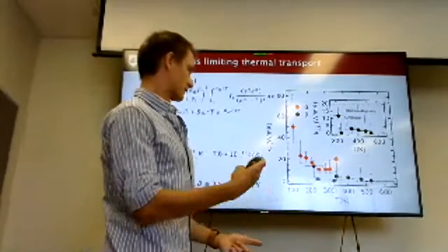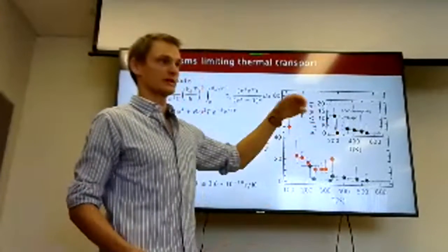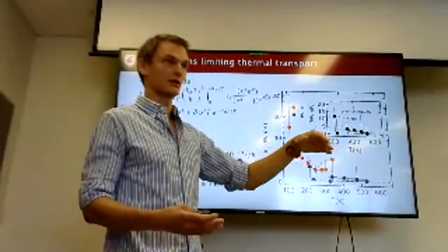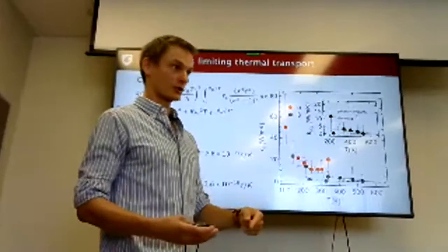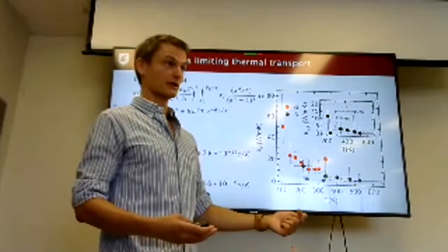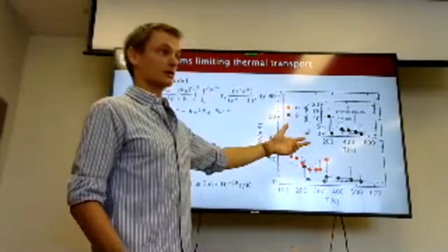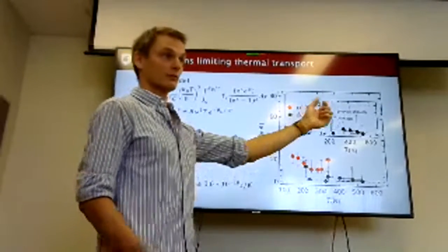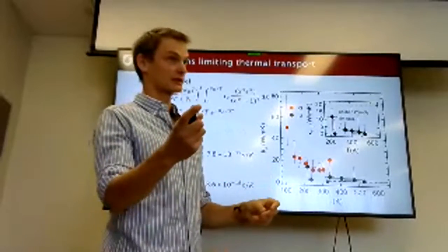But the very interesting thing that we should focus on here, right? Alpha having a low transport is not weird. It's a semiconductor. It's not going to be that great at transferring heat. Beta having a very low thermal transport is strange because it behaves as a metal electrically, but it behaves as an insulator thermally. That's why it made such a good thermoelectric material before. The heat couldn't leave. So you could heat up an area locally, the electrons can leave, the heat can't.